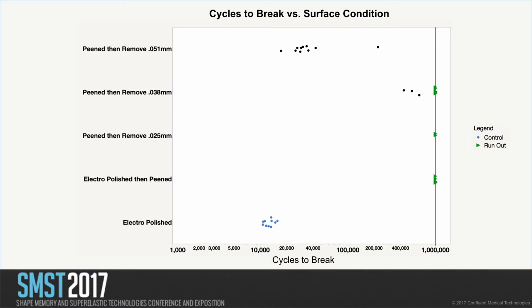Moving up to the final state, we start to see some interesting behavior. You notice that the fatigue performance actually starts to decrease. When we think back to the previous slide with that compressive residual stress plot, that makes sense, because as we're removing material, we're removing that compressive residual stress layer, which negates the benefits in fatigue life that we get from peening.